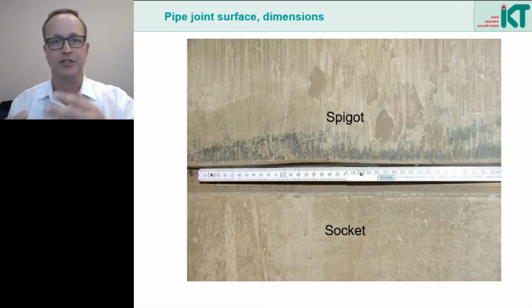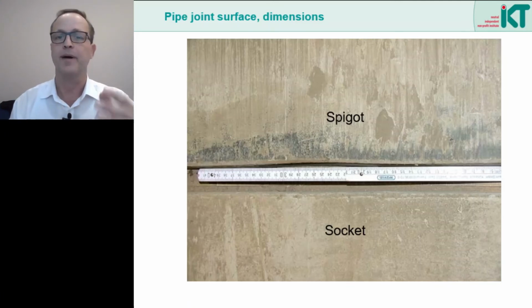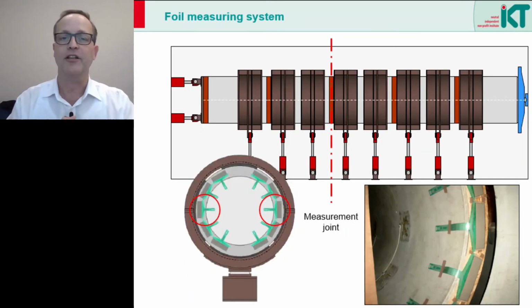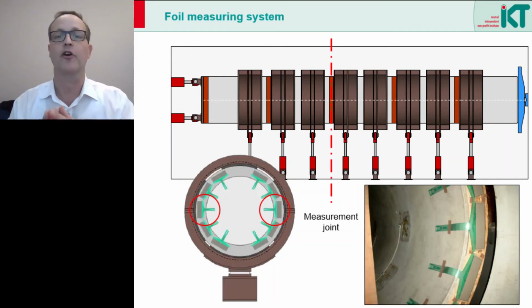Spigot end and socket are obviously not ideally parallel to each other. The pipes are usually manufactured vertically with the spigot end pointing upwards. In consequence, the spigot end in particular can have an uneven surface. In our large-scale tests, we then looked in more detail at the stresses that occur in the pipe joints, depending on which pressure transmission material is used.